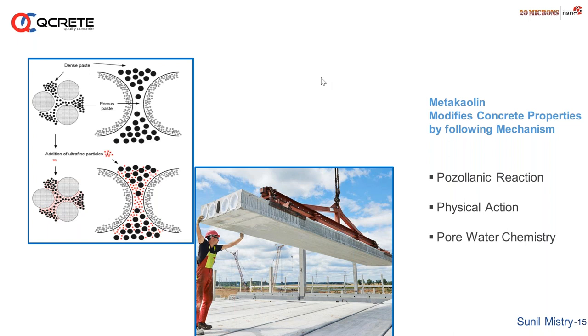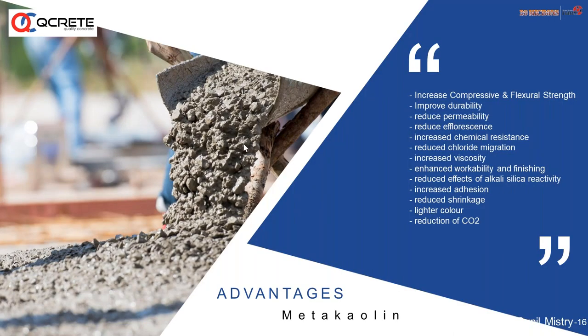On the upper side, you can see there is a paste, and when you add this material into the system, the red dot, you can see the finer material takes the place where the water was, and it fills the gap. So the concrete becomes much denser. By using metakaolin in the concrete system, there are a few advantages mentioned here. To get performance concrete, high compressive strength and flexural strength can be achieved, and durable concrete is possible because it drastically reduces permeability.